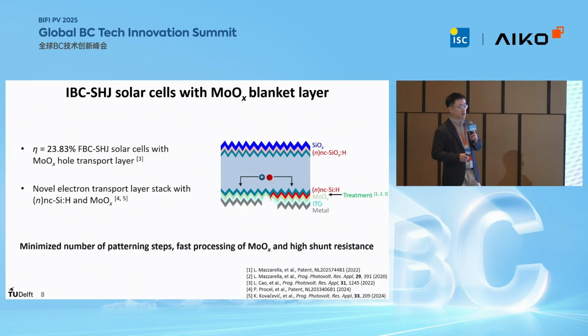With this IBC design, we can reduce the number of patterning steps, and also we have a faster process of molybdenum oxide because it's only 1.7 nanometer, either via sputtering or evaporation, and also featuring high shunt resistance.